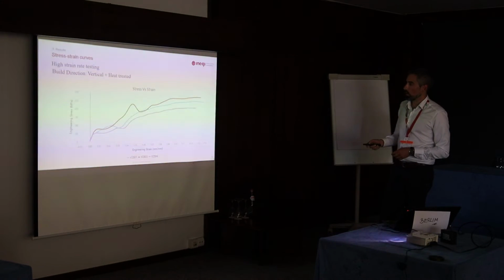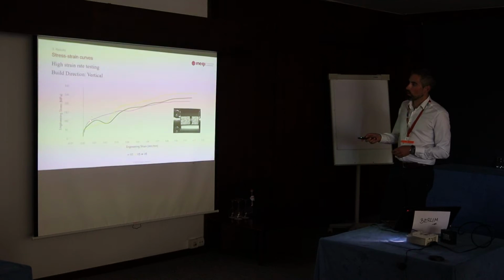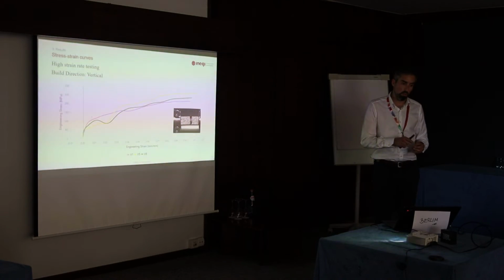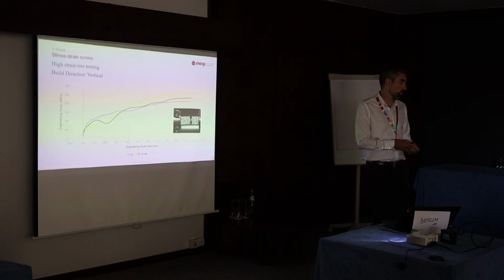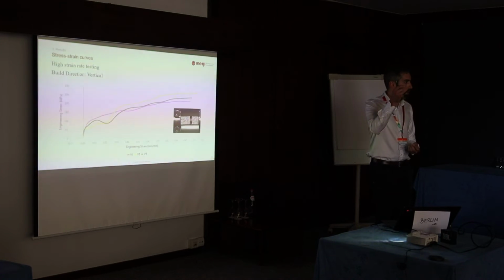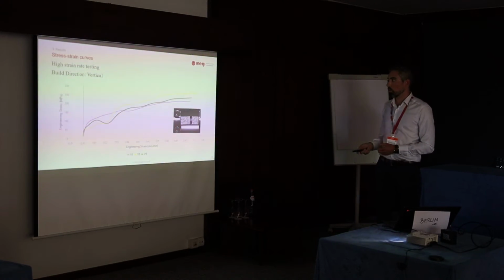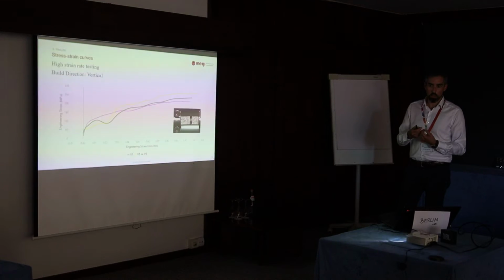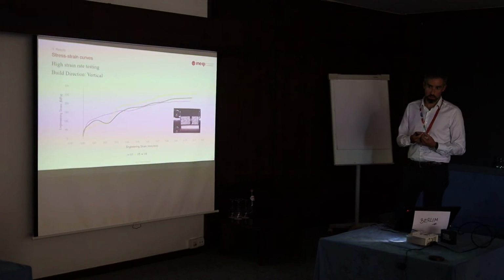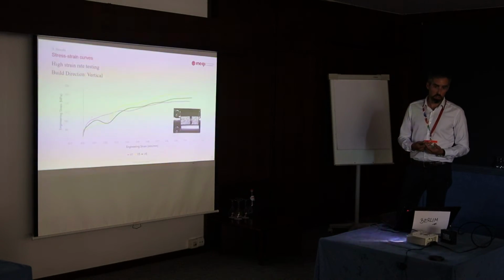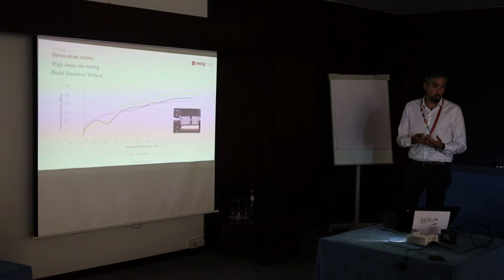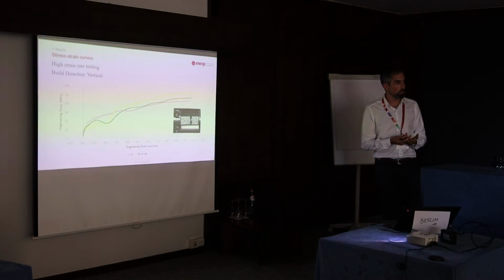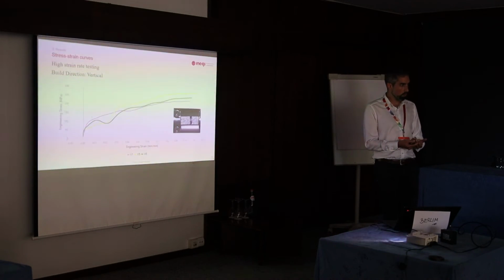You can see here that there's a lot of fluctuation in the signal at the beginning, especially because we are going very fast from no excitation to a very high deformation. So it's very common that in the beginning of this test, a material such as one produced by additive manufacture has this non-linear behavior because of the way the wave propagates through the material.